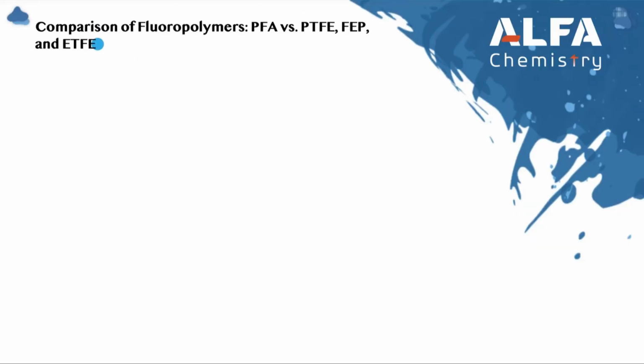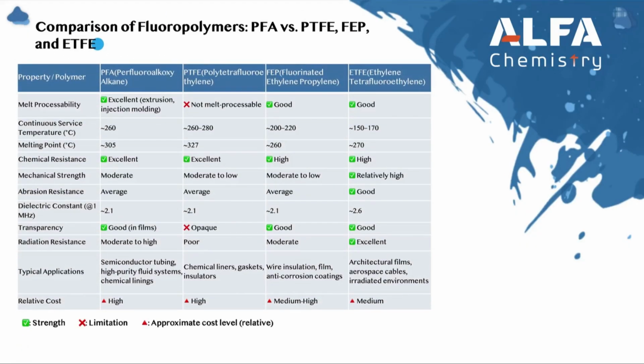When compared to other fluoropolymers such as PTFE, FEP, fluorinated ethylene propylene, and ETFE, ethylene tetrafluoroethylene, PFA balances high-temperature performance with processability. While PTFE surpasses all in terms of chemical inertness and dielectric performance, it lacks the thermoplastic nature that makes PFA favorable for complex parts. FEP, while melt-processable and chemically resistant, operates at a slightly lower temperature range than PFA and lacks its mechanical robustness. ETFE, though mechanically strong and more impact-resistant, sacrifices some chemical and thermal resistance. Hence, PFA stands as a high-end compromise, ideal where both high purity and structural integrity are non-negotiable.